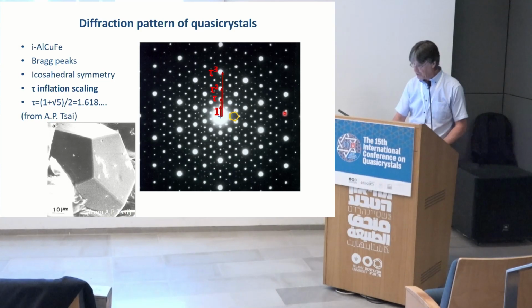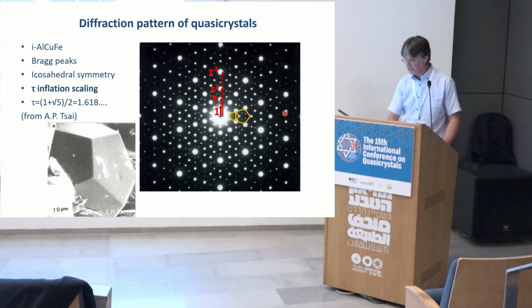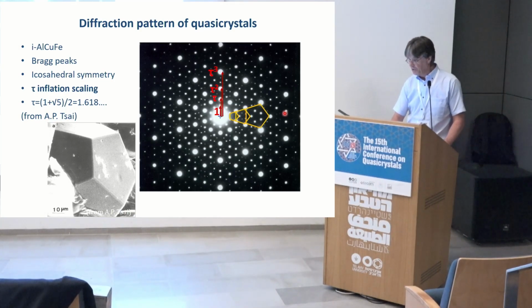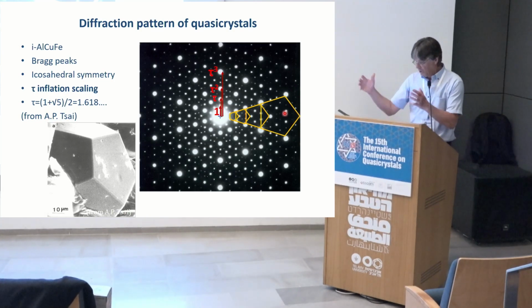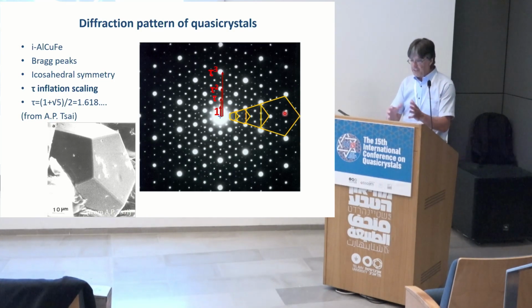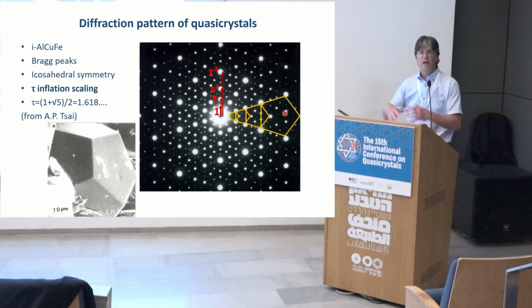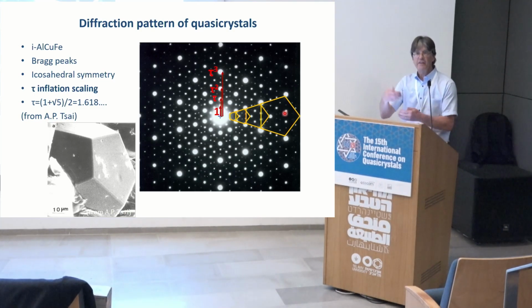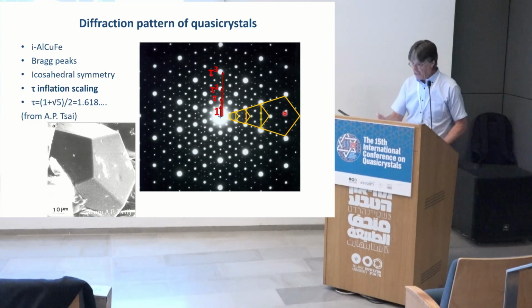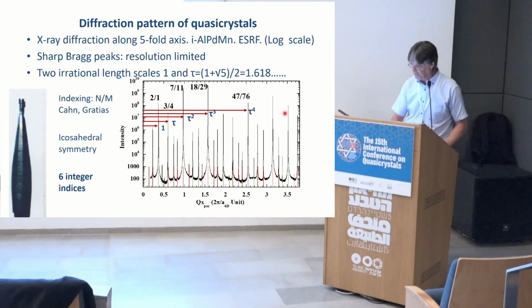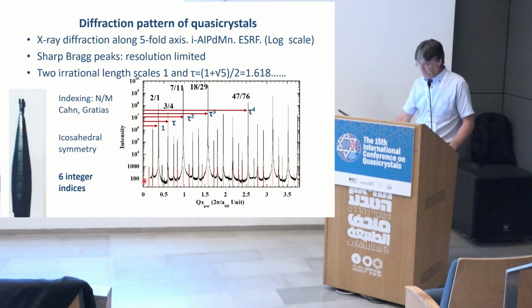You can also notice that you have pentagons that are scaling up with the same golden mean up to this length scale. So these are the two kinds of signatures. We have the symmetry and these two length scales that are showing up, and moreover, the Bragg peaks, which are very sharp. It's another example, just now using X-ray diffraction, and please notice that the scale here is logarithmic.